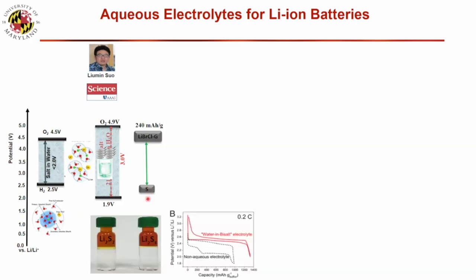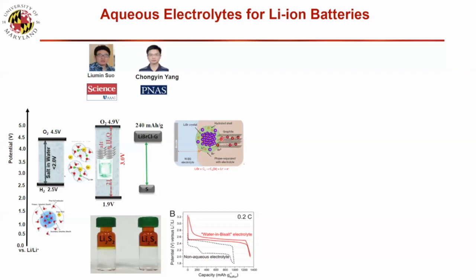For example, sulfur. In organic, the high-order polysulfide dissolves, but in water-in-salt, they are phase separated, because this lithium sulfide is also hydrophilic and the electrolyte, lithium TFSI 21 molar, is also hydrophilic. They both attract the water, but they are phase separated. Then we have the opportunity to charge and discharge in a liquid reaction without a shuttle. Also, we can use lithium chloride and lithium bromide, and use chloride and bromide inserted into the graphite, because they are phase separated and bromide and chloride cannot diffuse back. So this is a new opportunity.